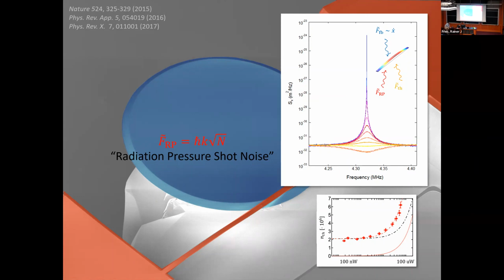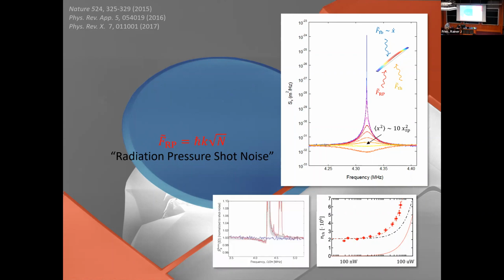And you see actually, eventually the noise floor goes below the shot noise of the measurement. And this is because basically that feedback is introducing correlations between the intensity and phase of the optical field. This is not squeezing, it's called squashing. But it's an interesting regime to be in. Actually, if you did make an out of loop measurement, in this experiment, we're cooled down to around 5 photons. So if you did make an out of loop measurement of the intensity of the optical field in this situation